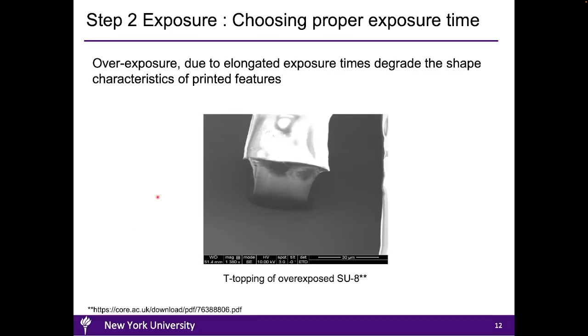The exposure time is another important factor for successfully transforming the mask image into the photoresist. Specifically, the number of photons that impinge onto the exposed region of the photoresist determines the quality of the image. Since there are a finite number of photoactive compounds within the exposed regions of the photoresist, the number of required photons for driving the desired chemical reactions must be adjusted.